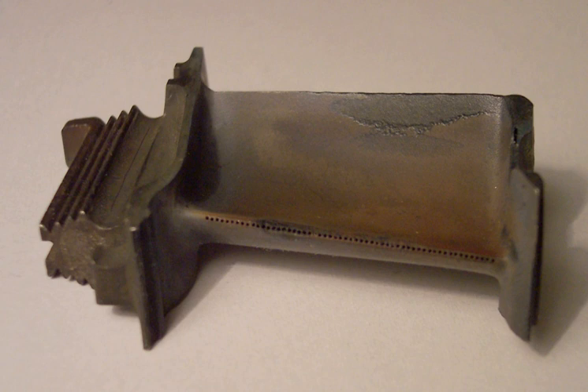In order to improve the oxidation resistance of these alloys, Al, Cr, B, and Y are added. The Al and Cr form oxide layers that passivate the surface and protect the superalloy from further oxidation, while B and Y are used to improve the adhesion of this oxide scale to the substrate. Cr, Fe, Co, Mo and Re all preferentially partition to the gamma matrix, while Al, Ti, Nb, Ta, and V preferentially partition to the gamma prime precipitates and solid solution strengthen the matrix and precipitates respectively.